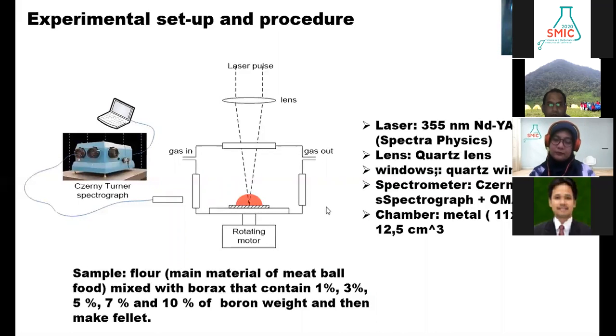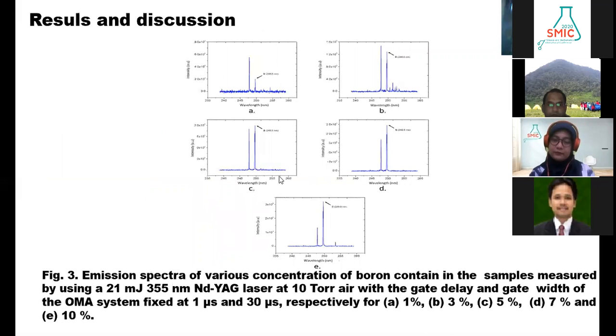The result of the experiment is like that. This is the spectrum recorded from the 5 different samples. This one for 1% of boron concentration, and this one for 3% of boron concentration, this for 5%, this for 7%, this for 10%.